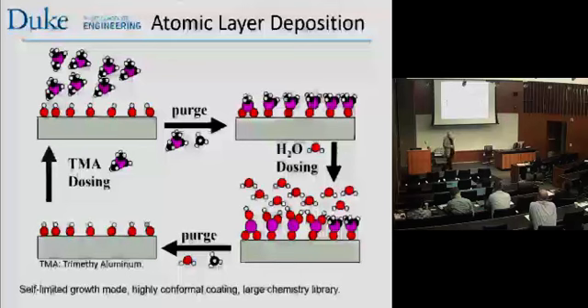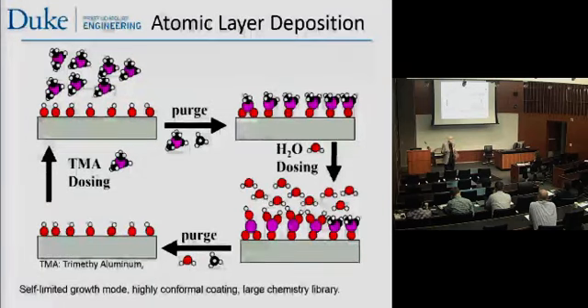So just a second on atomic layer deposition. This is an approach that's become very popular just in the last 10 years. It's a process by which we use self-terminating growth layers such that we can grow on any surface, even non-conformal ones. We generally think of aspect ratio: if I'm a semiconductor person, can I grow inside this via or these deep trenches? If I'm going to sputter or chemically vapor deposit, I have to worry about that aspect ratio. With atomic layer deposition, you don't have to worry about that, because a layer of material goes and terminates the surface, and another layer can't grow on it. By the chemistry itself, you can't grow two layers at a time.